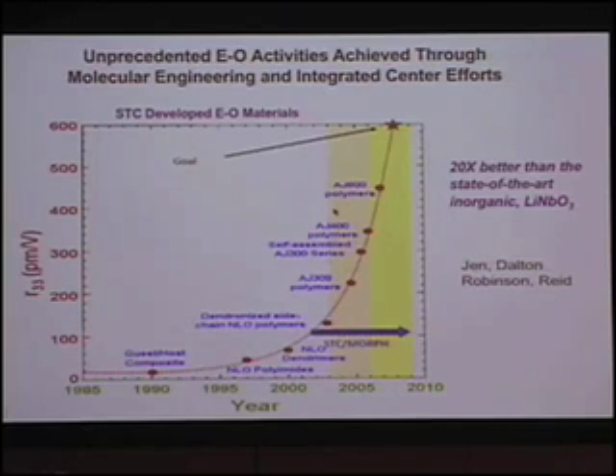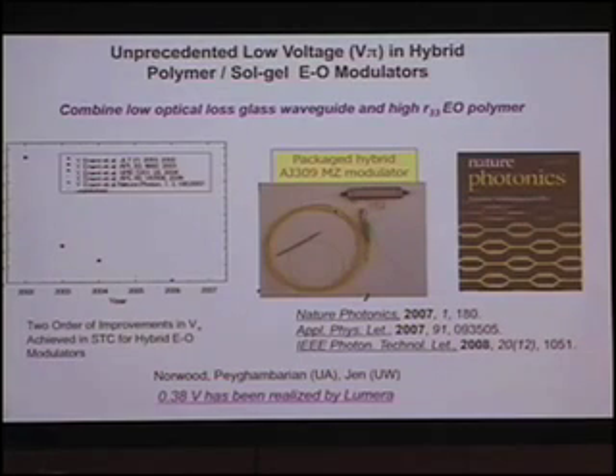So this is a chart to show you one of the integrated efforts within the NSF-funded STC at the University of Washington. In the past few years, we have developed electro-optic material that now reaches an electro-optic coefficient around 600 picometer per volt. This represents about 20 times that of your best lithium niobate device performance. And with that development, when you work with very clever device engineers, they can really take advantage of this ultra-high electro-optic coefficient and develop a device with ultra-low voltage to modulate.